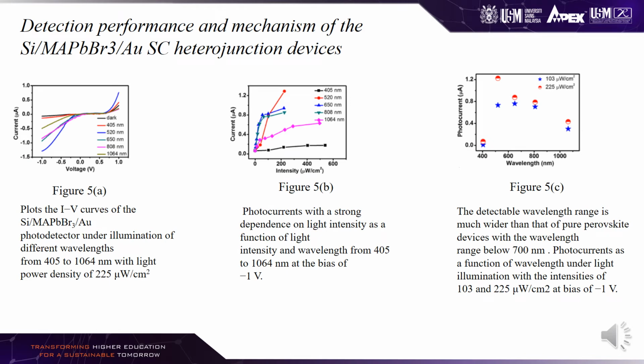This slide shows the detection performance and mechanism of the silicon MAPbBr3 gold single crystal heterojunction devices. The IV curve of the silicon MAPbBr3 gold photodetector under illumination of different wavelengths from 405 to 1064 nanometers with light power density of 225 microwatt per centimeter square is shown in figure 5a. Photocurrents show a strong dependence on light intensity as a function of light intensity and wavelength from 405 to 1064 nanometers at the bias of negative 1 volt, shown in figure 5b.